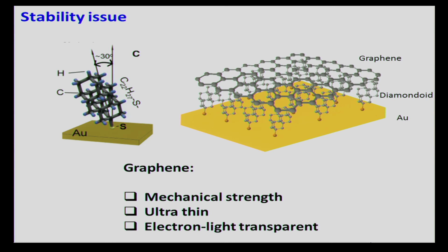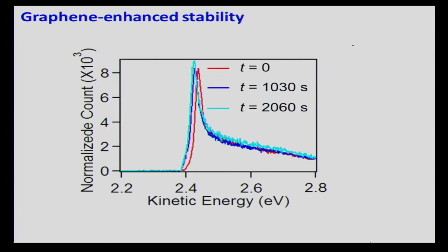But because it's very thin, only a monolayer of carbon, it's really transparent to electrons. So whatever electrons you extract from the diamondoid, you can still send into vacuum without being bounced back or sideways by this graphene coating. Again, we look at the number of electrons as a function of their energy. You can see that we preserve this really sharp, what we call single color or monochromatic, electron emission peak, and this can now be operated over a long duration of time.